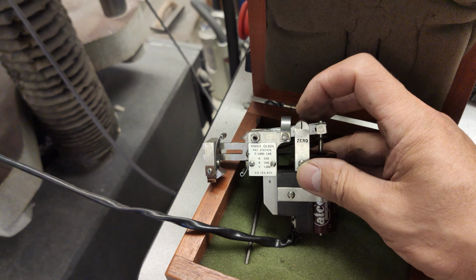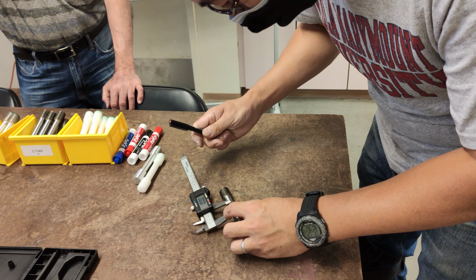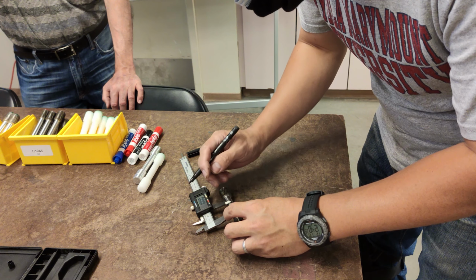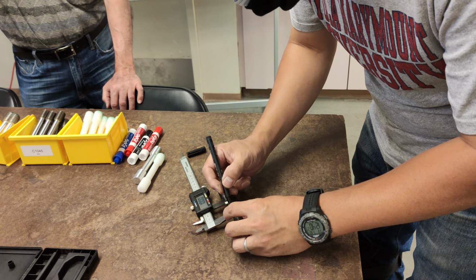Give or take. And then he is going to put 2 markers which will be showing the gauge length, and he is going to record 1 inch. Yeah, he's marking 1 inch, so that after we break the sample, we want to see how much distance the 2 markers travel. And then we're going to subtract the original 1 inch from this distance and divide it by the original 1 inch. That will give us the percent elongation, which is a measure of ductility.